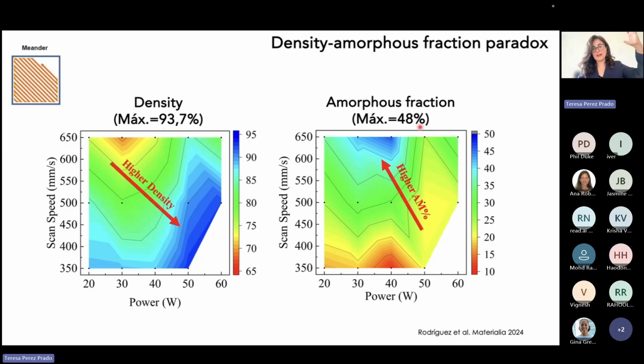This is very far from our target. Our target is 100%, no? So this is very far. And there is another aspect that was challenging, and it's what is indicated by these arrows. As you can see here, the amorphous fraction under these processing conditions increases when we increase the scan speed and we decrease the laser power.